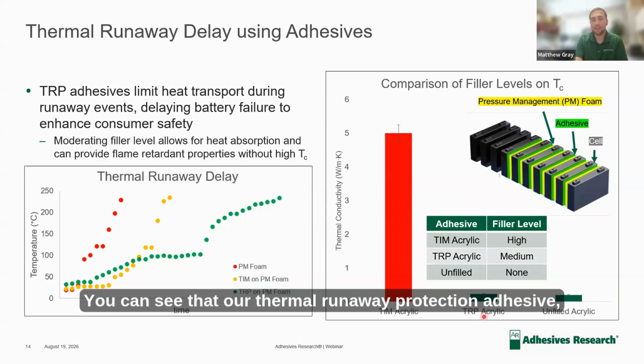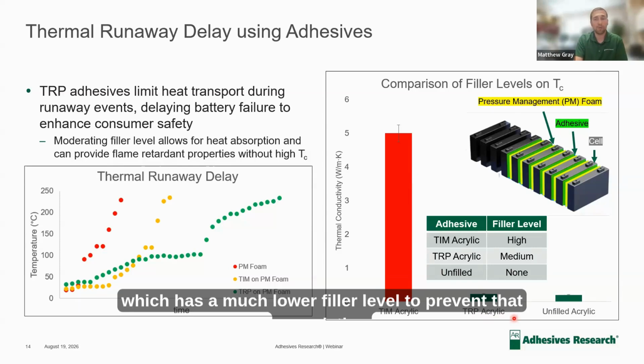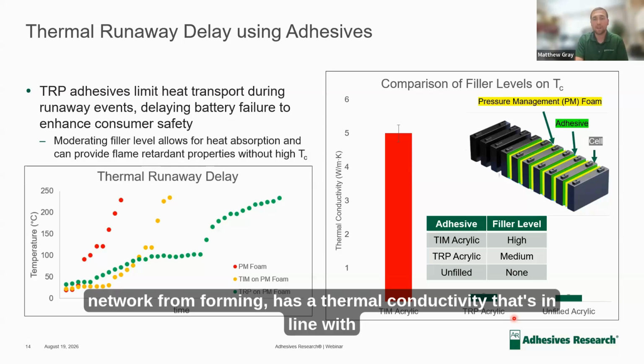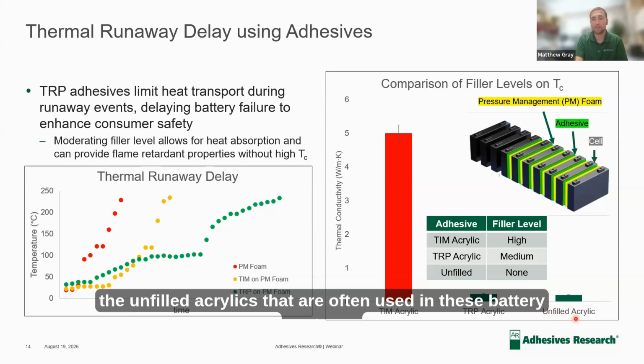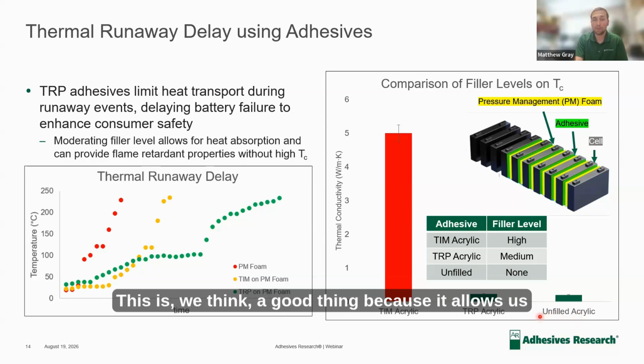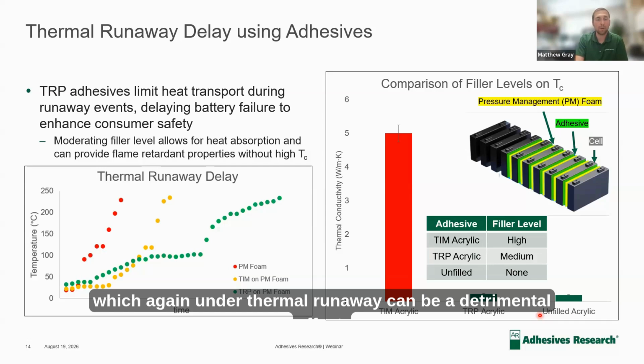You can see that our thermal runaway protection adhesive, which has a much lower filler level to prevent that percolation network from forming, has a thermal conductivity that's in line with the unfilled acrylics that are often used in these battery systems. This is, we think, a good thing because it allows us to have a lot of fillers to help with thermal runaway protection, but not reach that percolation threshold, which again, under thermal runaway can be a detrimental effect.